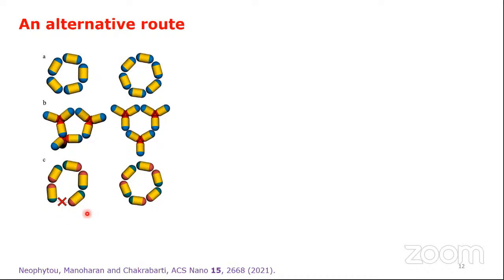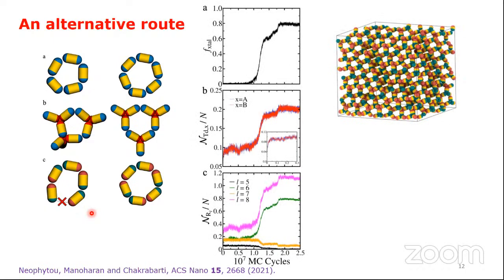We ensure that there are no thermodynamic driving forces for the formation of AB bonds. Such specificity in the patch-patch interactions could be realized using DNA-mediated interactions in synthetic colloids. Seeing is believing. This route also yields the crystal. The formation of 6 and 8-membered rings signals crystallization, which interestingly in this case occurs in 2 steps, with a growth of tetrahedral ordering prior to nucleation.